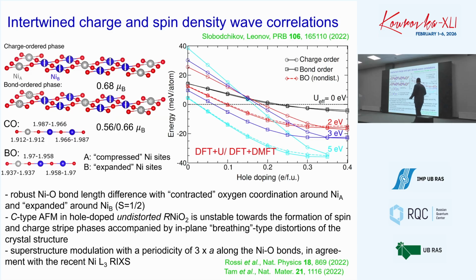Our answer to this question: we try to model this behavior with a combination of different techniques. We try to optimize the lattice, and it turned out that the lattice is pretty important for this material, to stabilize some tiny lattice deformations. But those tiny lattice deformations result in some kind of ordered phase, which we call the bond-ordered phase, shown here.